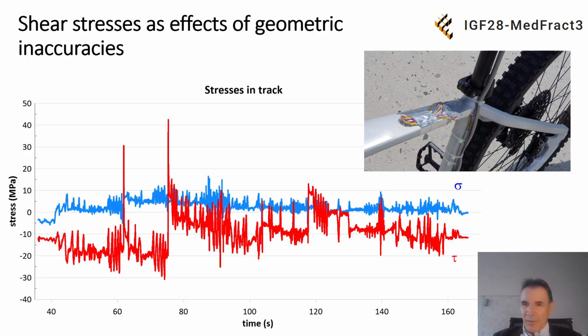These are the stresses in this point. This part joins the seat tube and head tube, and the loading here is relatively stable without a big gradient, so the shear stress results are very valuable. These shear stresses are not present in the standards, because the standards do not consider geometrical inaccuracies. The reality is that the red stresses are comparable with the stresses from bending when we see these values.